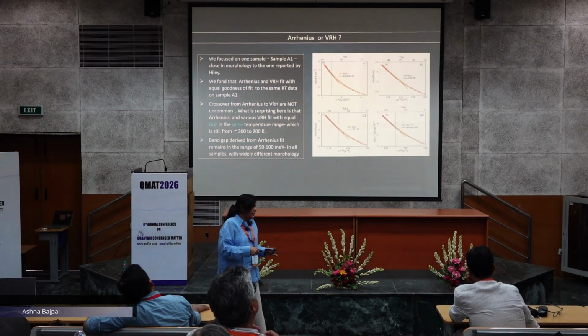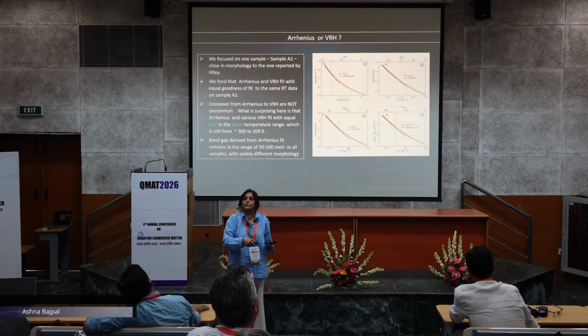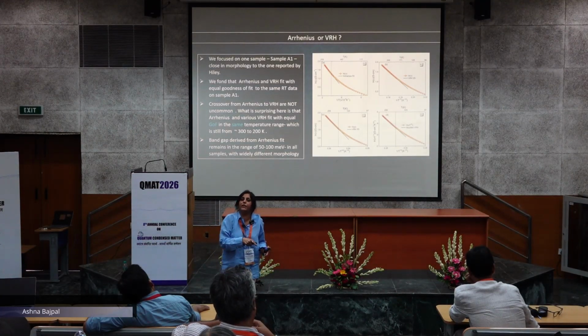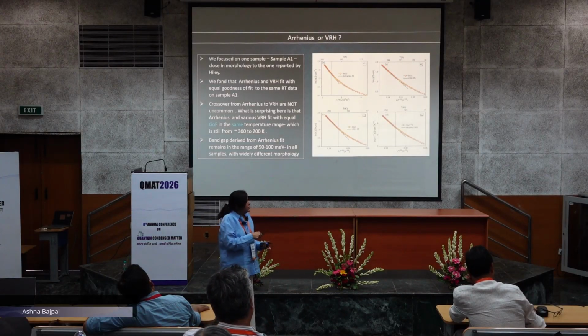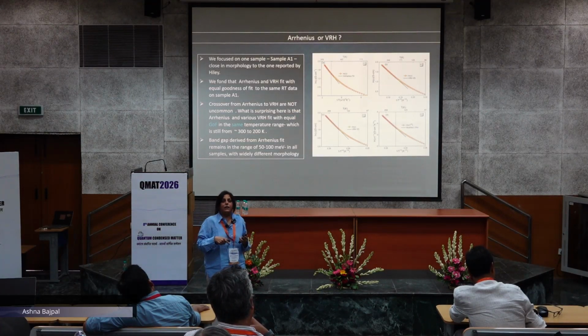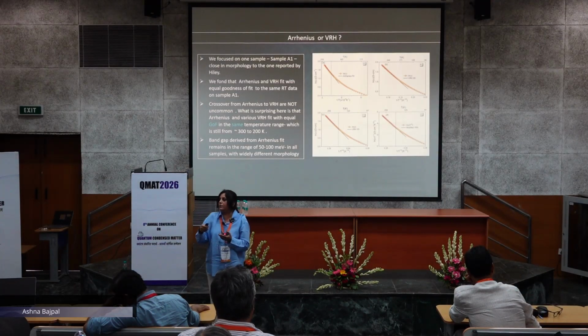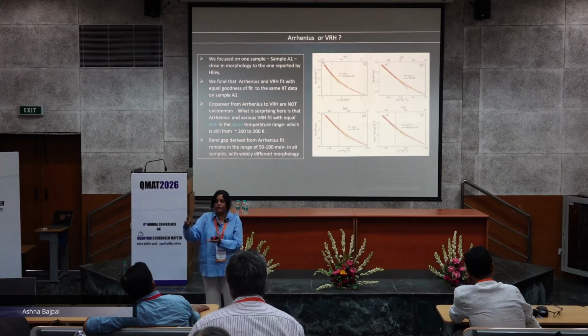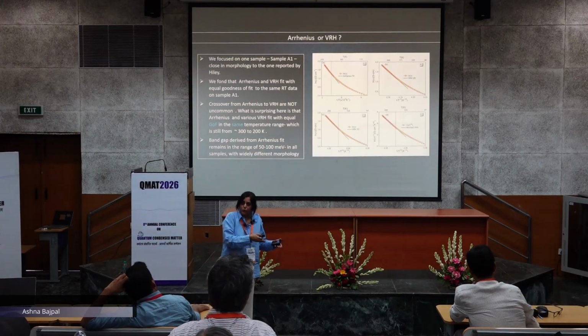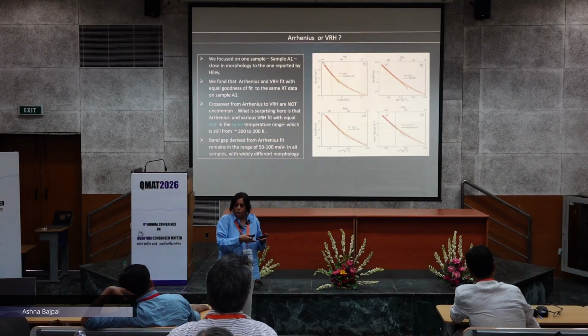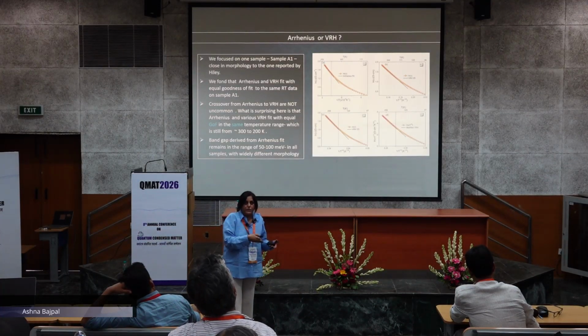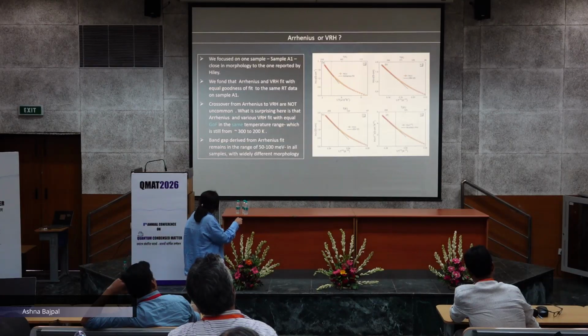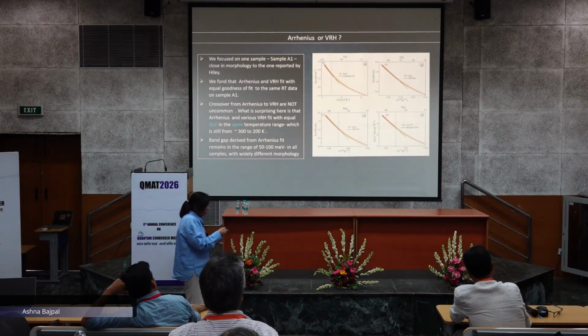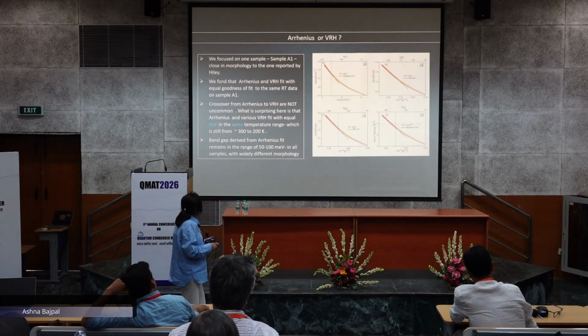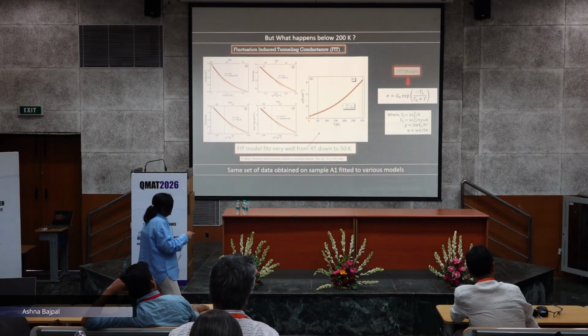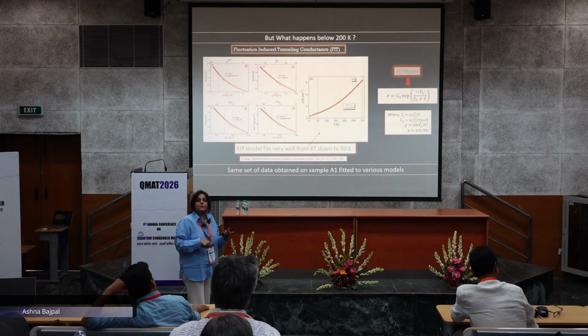It is somewhat like the problem of spin glass, where various models will fit your experimental data, and it's very hard to figure out which is the best model. Typically you find a crossover from Arrhenius to variable range hopping at the lower temperature region, rightly so, when defects play a more prominent role. But in our case we found that in the same region all these models fit with equal goodness of fit. And so this brought us to a relatively lesser known model.